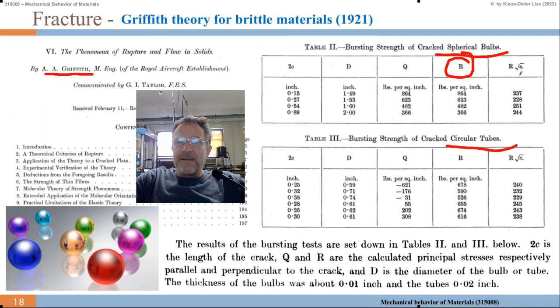He found that R over square root of C is more or less a constant: 237, 228, 251, 244. He also varied the 2C a lot, and he varied the diameter, but R over square root of C turns out to become a constant in his experiments.